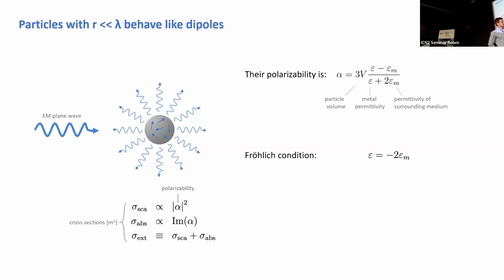Of course, there is no single material where this can be perfectly happening. In fact, the permittivity is always a complex function, so you never have a perfect epsilon of -2. But you can imagine that if epsilon is in the vicinity of -2, the polarizability will diverge, and the scattering and the absorption cross-section will diverge, will become very large. And so your object interacts with light very strongly. It extinguishes a lot of light.